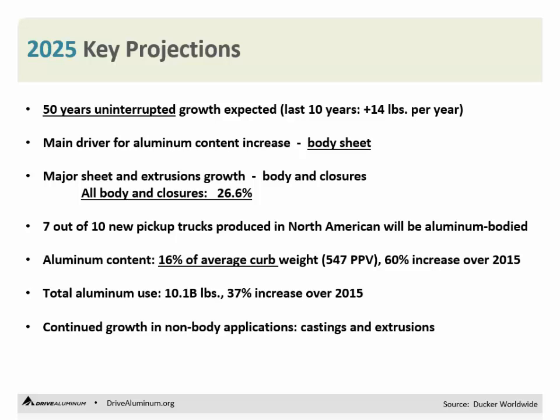Seven out of 10 new pickup trucks produced in North America will be all aluminum bodied. 16% of the curb weight of the average vehicle will be aluminum, and that's a 60% increase from the average curb weight of 10% in 2015. Total aluminum use in the marketplace will be 10.1 billion pounds, or a 37% increase over today's total aluminum consumption. And the non-body applications of aluminum will continue to grow at a steady but reduced rate due in majority to the fact that they're nearing saturation in many of the applications they're in.